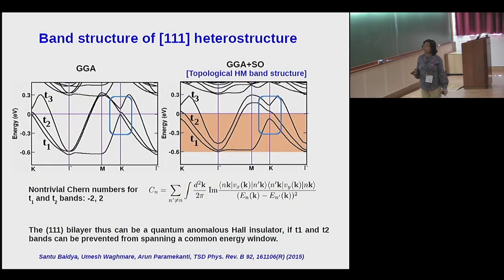Now what about the topological properties of it? This is the band structure in one of the spin channels, the conducting spin channel, the other channel being completely insulating. You see three bands that cross the Fermi level, and they are basically the rhenium t2g bands. This is the band structure in the absence of spin-orbit coupling, and this is the band structure in the presence of spin-orbit coupling. The spin-orbit coupling does have a significant effect by changing the details of the band structure. And if you calculate the Chern numbers of these three bands, they are non-trivial.